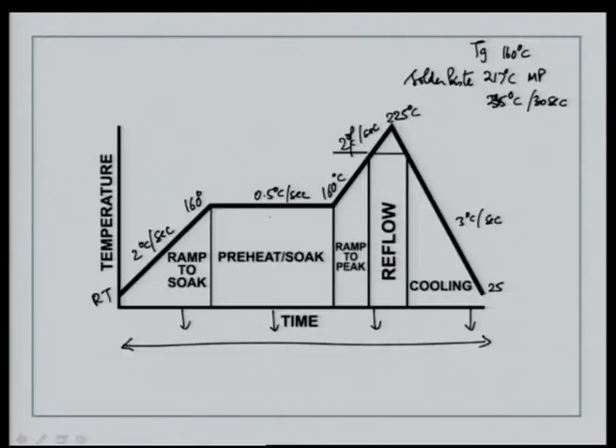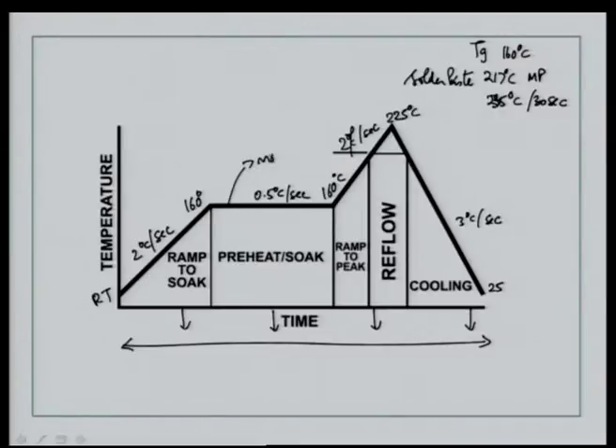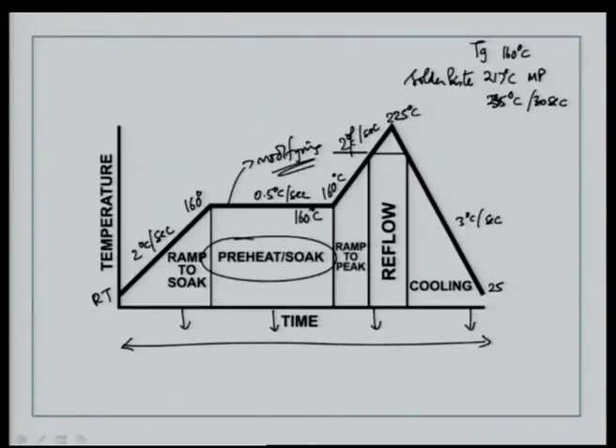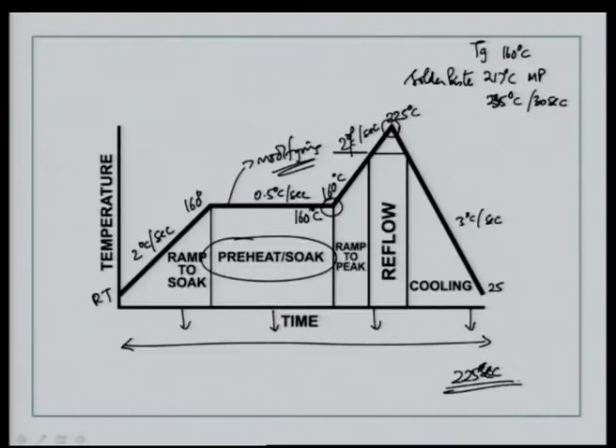You can split the soaking zone into two zones: from 160°C to 180–190°C with a quick ramp-up, and then from 190°C to 225°C as the reflow ramp-up. So you can consider modifying the zone boundaries based on the available information. The idea is to activate the entire system at 160°C, then move from 160°C to 225°C without a residence time, and then get back to room temperature gradually.